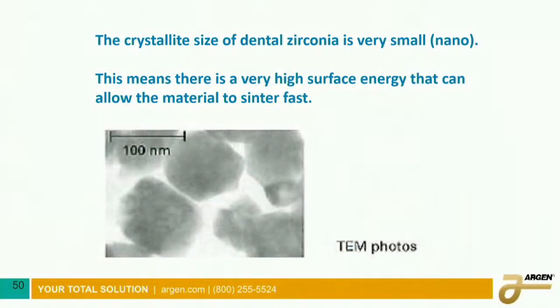So the instructions are going to be conservative, because we have to make sure that it's going to work every time if you follow the instructions. Okay? Now, there's always other things you can do, and one of the things that we're looking at now is trying to tap into this very high surface energy. The zirconia particles are very, very small. They're actually nano size, and here's 100 nanometers, and this is a zirconia particle that's floating around. And that means that there's a very high surface energy. If you could tap into that surface energy, then you could have this material sinter very, very fast, much faster than normal.